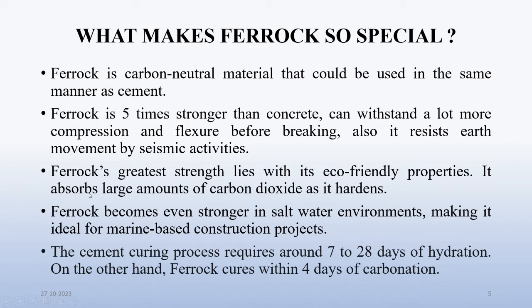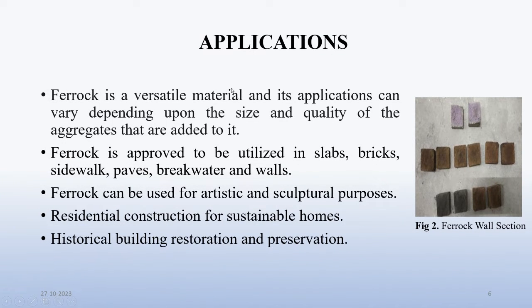Ferroc's greatest strength lies in its eco-friendly properties — it absorbs large amounts of carbon dioxide as it hardens. Ferroc becomes even stronger in saltwater environments, making it ideal for marine-based construction projects. The cement curing process requires around 7 to 28 days of hydration, whereas Ferroc cures within four days of carbonation.